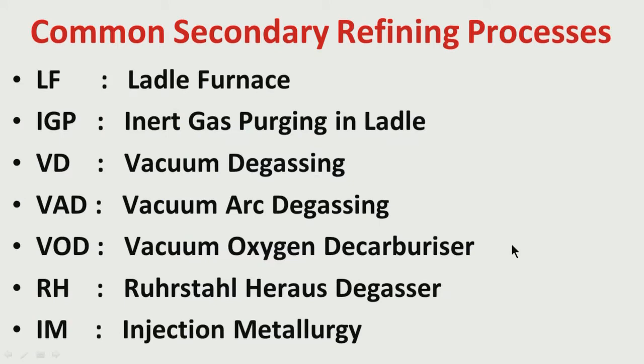Now, I had talked about what are the common secondary refining processes. I have talked about the ladle furnace, which is a very common process. Most of the steel producers today have a ladle furnace. I will come to what the ladle furnace can do, what its capabilities are. Then inert gas purging in the ladle. This is very simple. Through the bottom of the ladle, there is a gate through which you can pass inert gas, say argon. So it is possible to make a good circulation in the bath. The bath becomes homogeneous. This helps in some reactions like deoxidation reaction, floating off deoxidants, and related advantages are there.